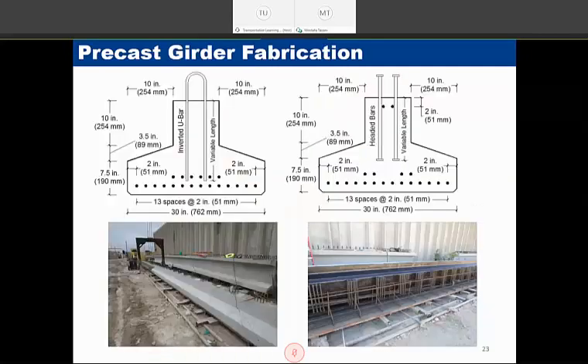The inverted T-beams were prepared and cast in 2 days, 1 per each. And the girders were 20 inch deep, post-tensioned with grade 270 strands, and either inverted U-shape and double headed studs were used. I would like to also mention that 2 post-tensioning tendons were provided at the end and harped at the end to make sure that the bridge doesn't crack at the end.